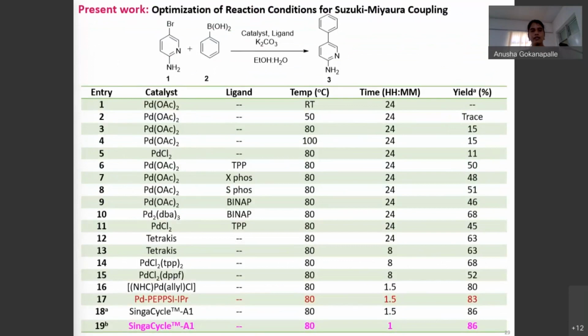Present work: optimization of reaction conditions for Suzuki-Miyaura coupling reaction. Here we are preparing pyridine-type derivatives. For that, we have taken 2-amino-5-bromopyridine. This is the model reaction for optimization. First, we started the reaction with palladium acetate without additional ligand, and we did not get any yield. Later, we added ligands to the catalyst, and we observed moderate yields. Later, we switched to palladium NHC catalyst, and we got better yields when compared to catalyst plus ligand.